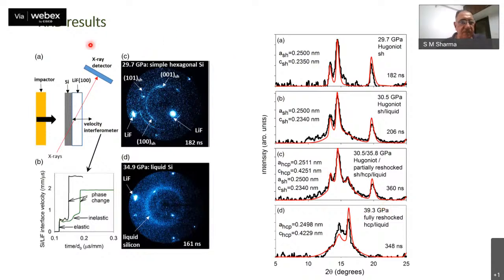Here is the nature of experiments which were done. There is an impactor, which makes this silicon, which is a single crystal silicon oriented along 100. It is backed up by lithium fluoride. At this interface, gold is deposited, which acts as a reflector for the velocity interferometer, VISAR. And when the shock is launched into this and is traveling, let us say, some distance into silicon, the X-ray pulse is launched into this, and the diffraction is recorded at various pressures.